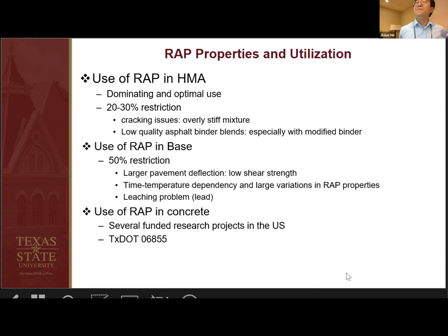Maybe some of you are not familiar with RAP. RAP is reclaimed asphalt pavement. It's essentially demolished asphalt pavement waste, but processed as aggregate, and traditionally it has been widely used in HMA to replace both binder and aggregate. However, adding RAP in HMA, hot mix asphalt, has some problems, primarily due to the cracking issue. Texas DOT had an interest in using RAP in concrete. In addition, Florida DOT, Illinois Tollway, and Montana DOT all had RAP in concrete projects. So that's the background.